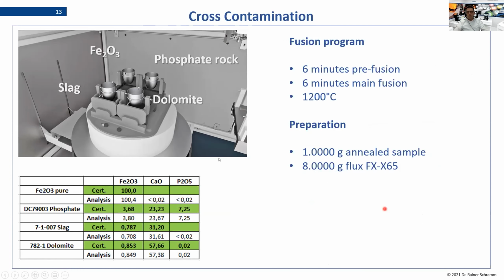The other important point was, how is the cross-contamination between the crucibles if you have different materials inside? So for example, if you have here pure iron oxide, a high phosphorus sample, a dolomite with high magnesium, calcium, and a slag. And if we look here at the analytical results, we can see that even the high iron is not really influencing the certified values we find in the analysis for the other materials. The same if we have high phosphorus and in the neighbor sample no phosphorus, we don't find phosphorus. So it is really safe from a classical fusion point of view regarding cross-contamination. But in case you have a sample which spits sometimes, you could use lids. So we have lids for all these crucibles, and then you close them, and then you are 100% safe that there is no cross-contamination in case your samples tend sometimes to spit around a bit.